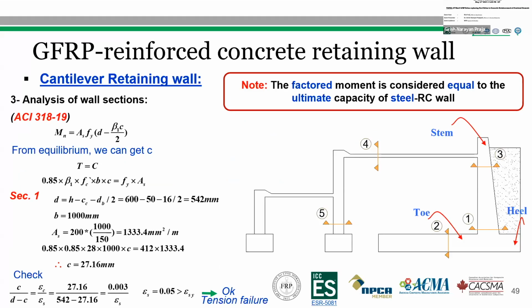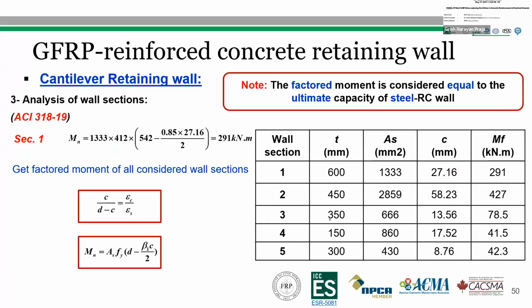And now we will analyze the retaining wall, and the factored moment is considered equal to the ultimate capacity of the steel reinforced concrete retaining wall. So for equilibrium, we can get the depth of neutral axis c and check the failure conditions using the strain distribution, which is subject to tension failure. Then the moment for each section was calculated using this equation, and the moment capacity of each section along with the provided steel area are listed in this table.